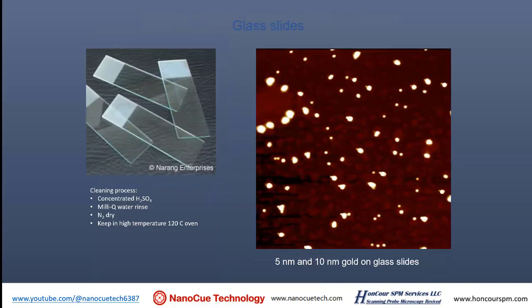Sometimes you can use glass substrate to deposit your species on it. But one thing about glass substrate is that it depends on the quality of it and how it was made. There's no guarantee the surface is very, very flat or homogeneous. Just be careful when you use glass slides. You have to image the glass slide without your sample. Just don't take a glass slide and say, hey, I'll put nanoparticles on it, and then I'll image with my AFM, right? What's wrong with this procedure?